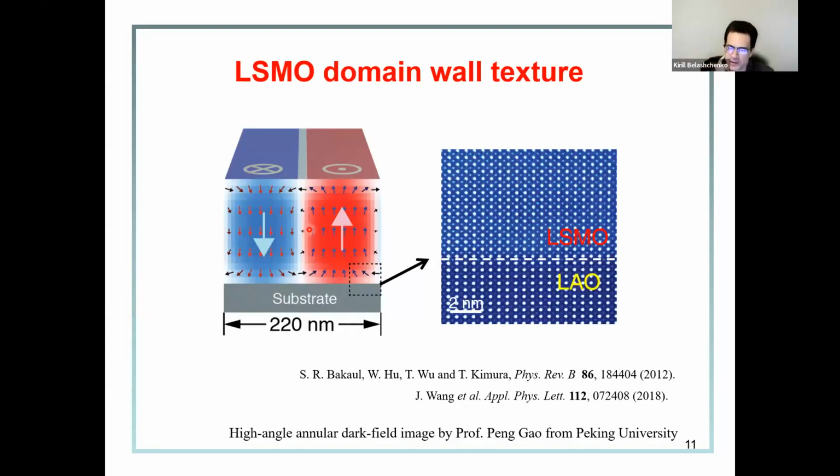But you have micromagnetic simulations, right? So to get this kind of texture with perpendicular spins, what do you need to put in? I think one major mechanism is the dipolar interaction. The integration of the dipolar interaction over a certain thickness favors these textures to minimize the total energy. So if the thickness is very thin, you will not easily have such textures, and if it's very thick, again, also not very likely. Only with these parameters, LSMO is about 100 to 150 nanometers in this region. Interesting.